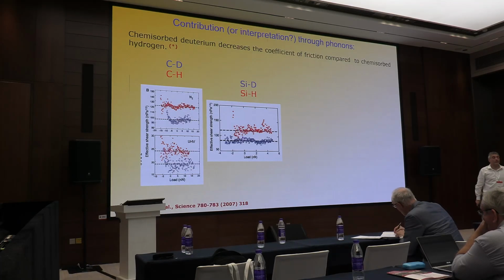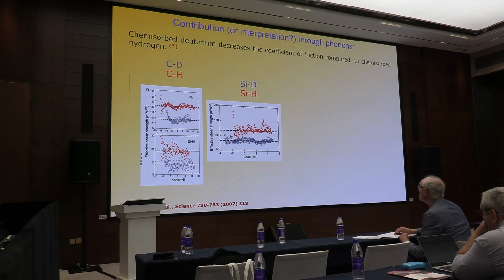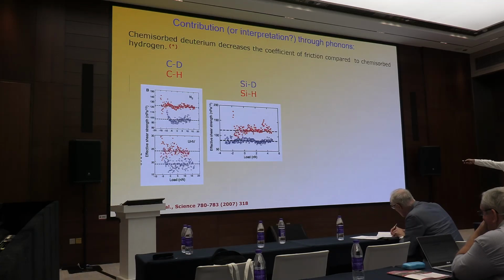It is an experimental result. In all cases, silicon or carbon with deuterium on surface, the shear strength, that is resistance of the tip sliding on the surface, is lower. Very important result. In the other case, when we have hydrogen, the friction, or in this case, the shear strength, is higher. We have more resistance when we have hydrogen on surface.